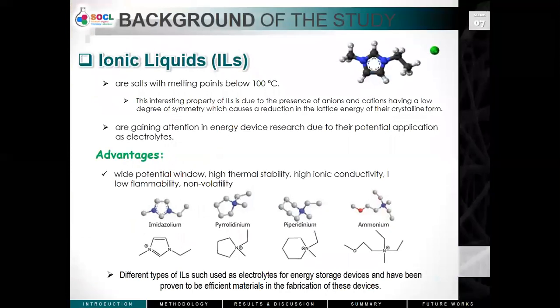In our previous works, we have demonstrated that ionic liquids as solvent-free electrolytes have shown promising electrochemical advantage over organic and aqueous electrolytes due to their low flammability, non-volatility, high ionic conductivity, and wide potential window. Similar to those reported in literature, the rheological and electrochemical properties of these ILs can be tuned such that the alkyl chain length and the choice of anion have an effect on the viscosity and on the capacitance of the supercapacitor.